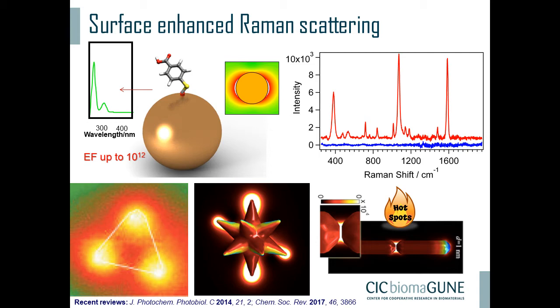Okay? Another way to increase the electric field enhancement is to bring particles close to each other. I also showed you before, and this is a very clear example. This is actually simply a gold colloid with spherical particles, quite dilute, and then we introduce organic molecules that are Raman active. If we measure the colloid in solution, the enhancement that we get is not enough to amplify the signal of the concentration of molecules that we had. But if you simply add sodium chloride to the solution, drive the aggregation of the particles, many molecules will be located at gaps between particles, and then immediately you get a spectrum like this, where you can identify basically all the vibrational peaks corresponding to those molecules. So simply by bringing particles close to each other, you get a much larger enhancement of the Raman signal.